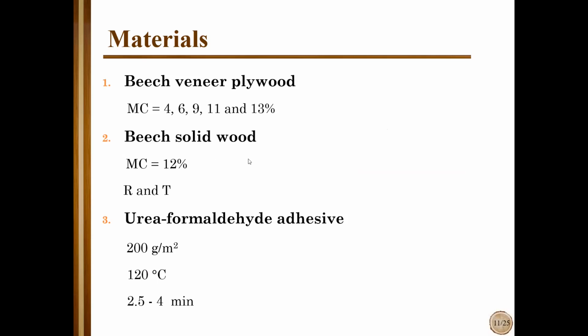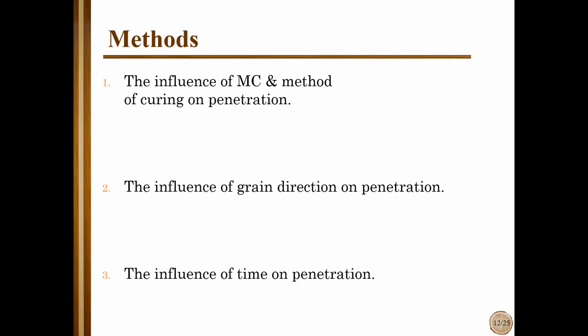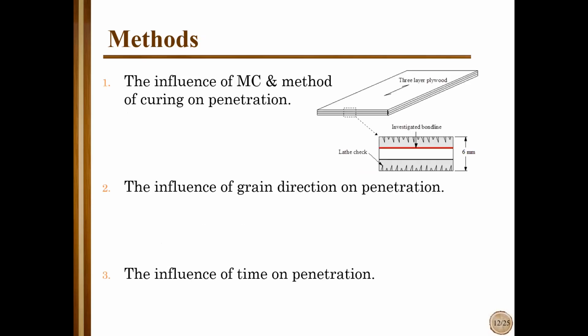Then another part was solid beech wood, different orientation, radial and tangential, and the adhesive was urea formaldehyde. This one is transparent when it cures. And now three different experiments. The first one was with plywood. We wanted to see how moisture content of the veneer impacts the penetration and curing of adhesive.